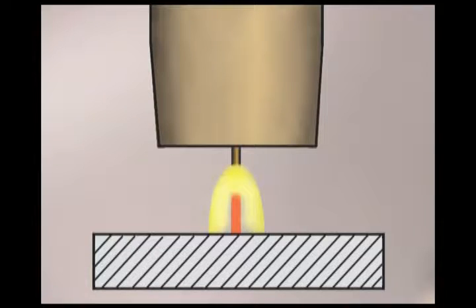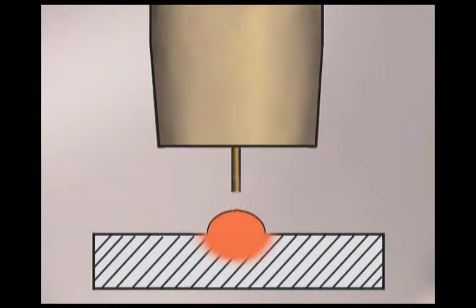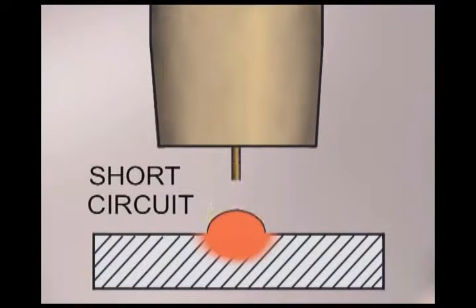The hot gases surrounding the arc melt the filler and the base metal, fusing them together. The continuously fed wire then overcomes the heat of the arc and contacts the metal again, heating it up, pinching it off, arcing, and fusing. This is called short circuit transfer, and the cycle happens 50 to 200 times a second, producing a distinctive sound and a weld puddle that's very easy to control.